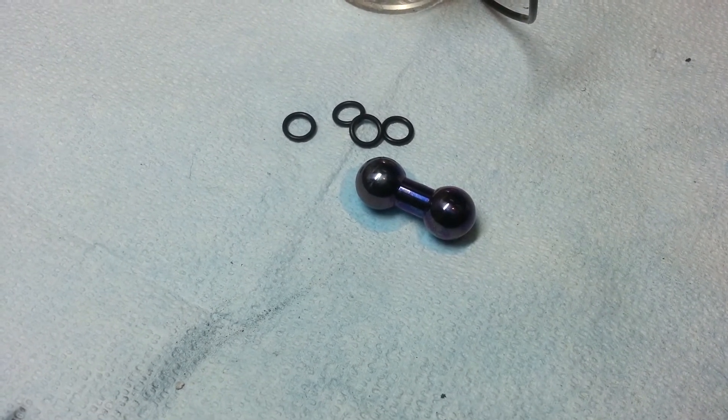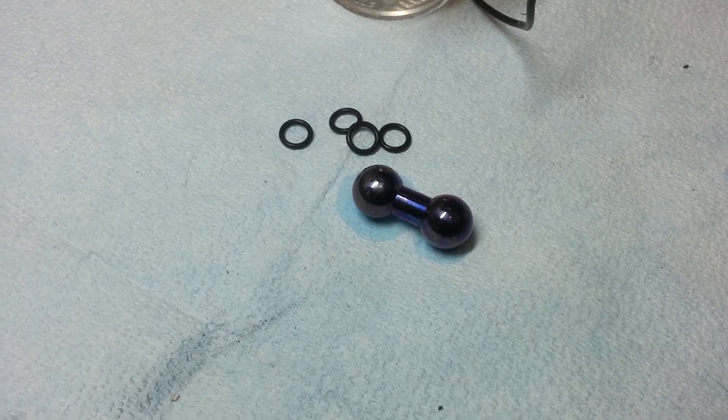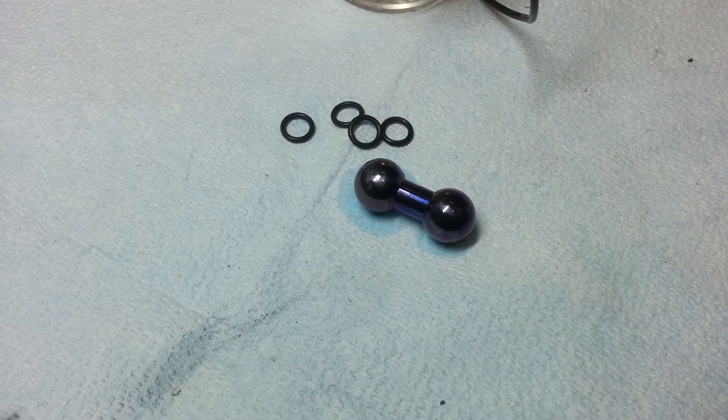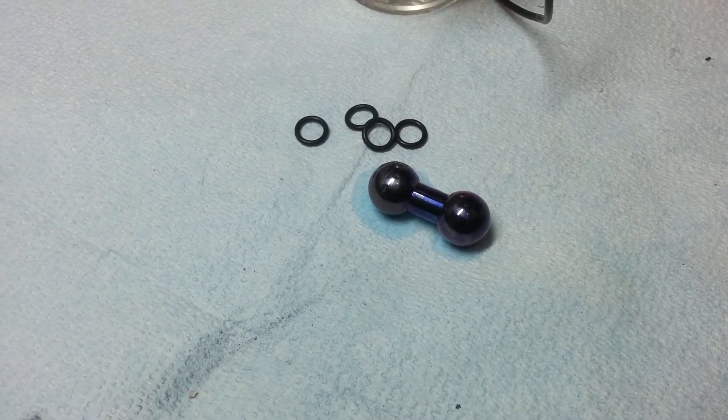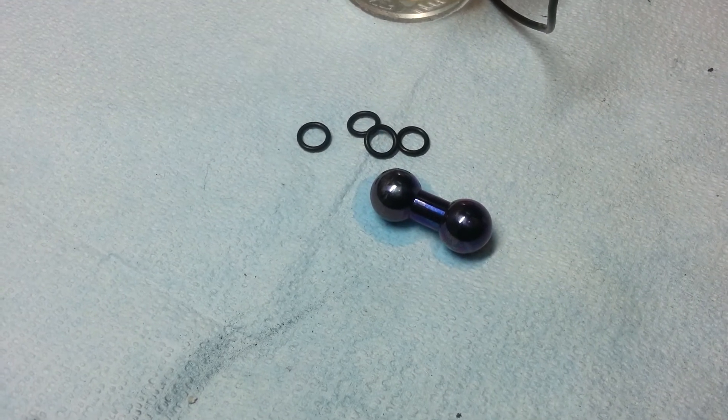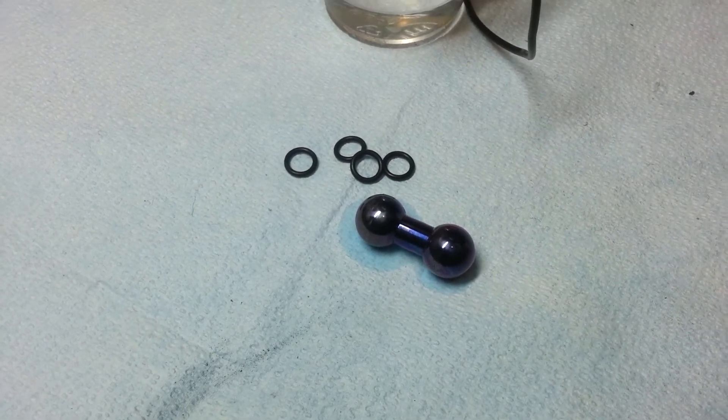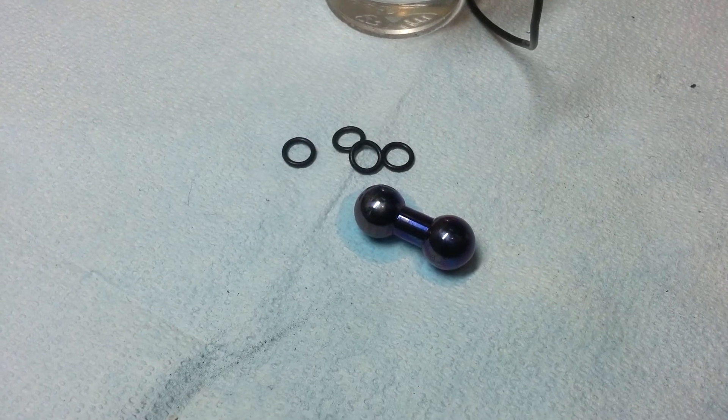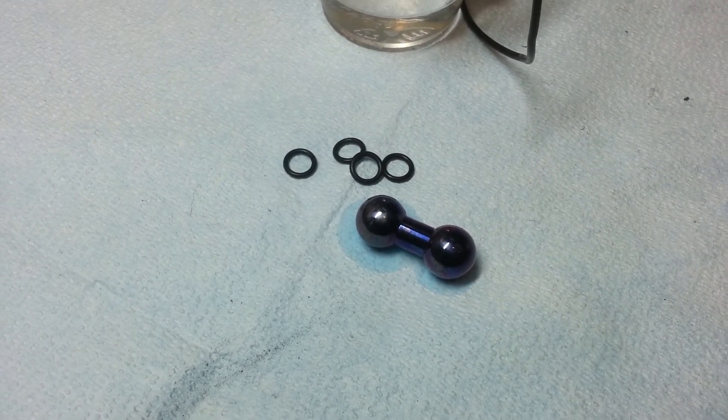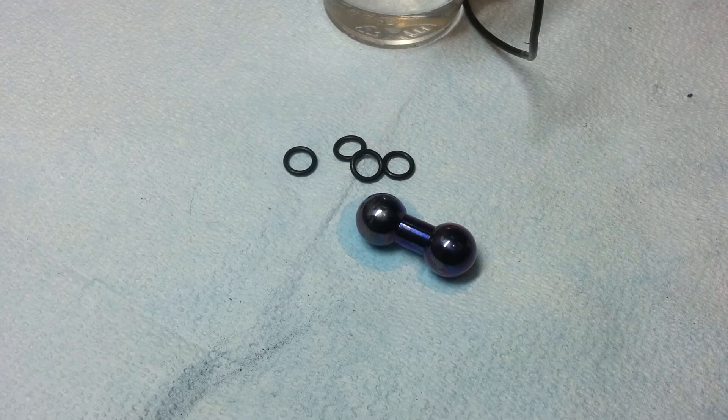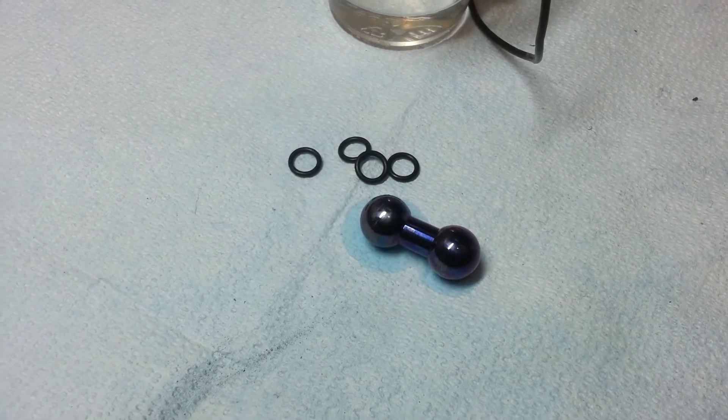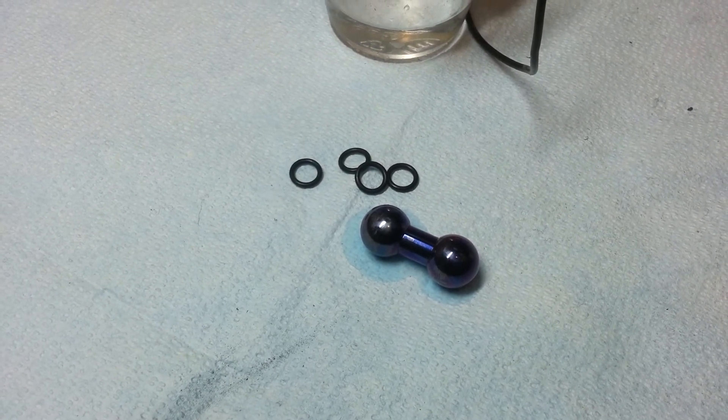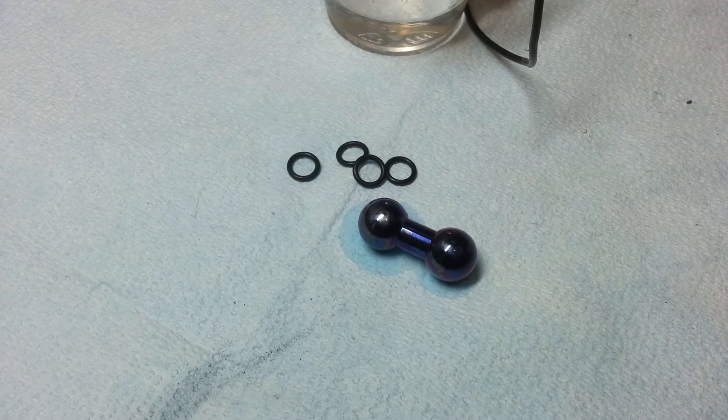What that's going to do is anywhere that the O-rings are touching the barbell, it's going to isolate the anodizing process. Basically it's going to block off the current from touching that part of the jewelry and therefore that purple color will stay behind. Any place that's not isolated with the O-rings will then change color as we're going to go to a higher voltage. This can be obtained in a number of different ways. I use O-rings because they're the easiest thing around. They also make like an anodizing tape that you can cut into little strips and things like that. So you can do all kinds of fun creative things with your jewelry.